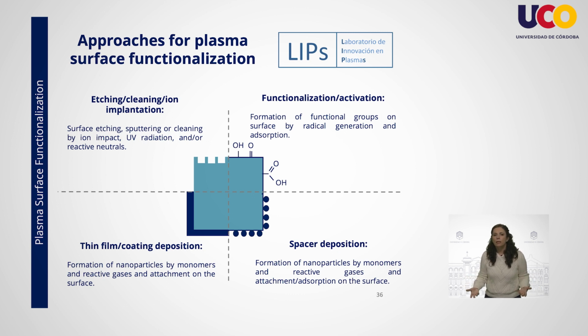Film deposition or coating is achieved by so-called plasma-enhanced chemical vapor deposition. In this case, the plasma contains reactive species capable of reacting with each other on top of the substrate to form a thin film. The polymerization may happen in the gas phase by the injection of precursor monomer and subsequent deposition on the substrate, or by free radicals which are formed on the surface and then react with gaseous radicals.